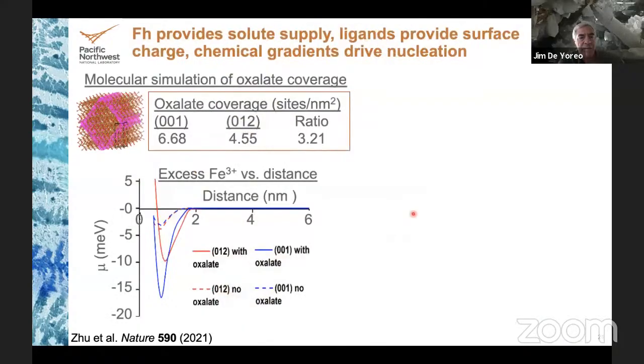So why does this happen? If we do molecular simulations, and we've also done measurements, you find that oxalate covers hematite very effectively on any surface that we measure or simulate. And it's different on different faces. So there's a different surface charge on the different faces. If you look at the excess iron concentration versus distance, what you find is a maximum in iron 3+ concentration about a nanometer away from the interface. And that maximum is different for the different faces of hematite.